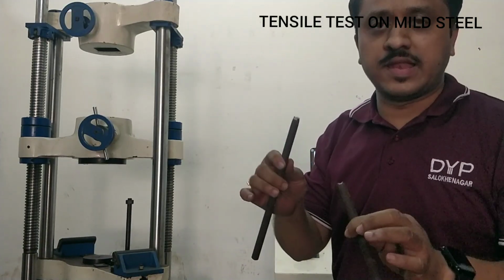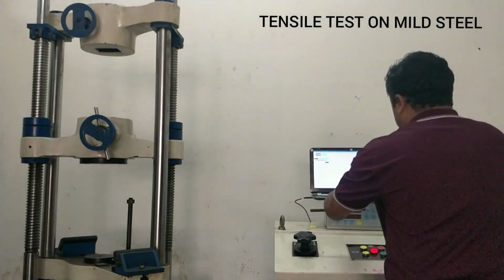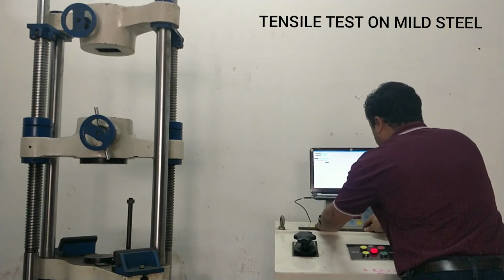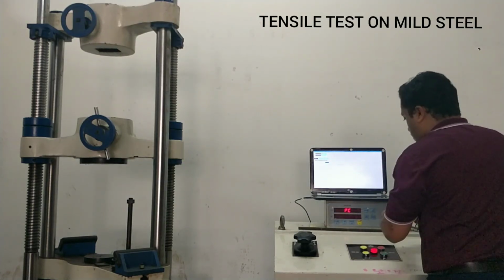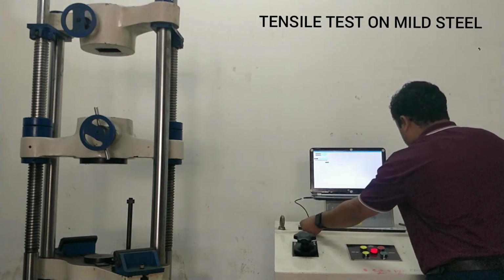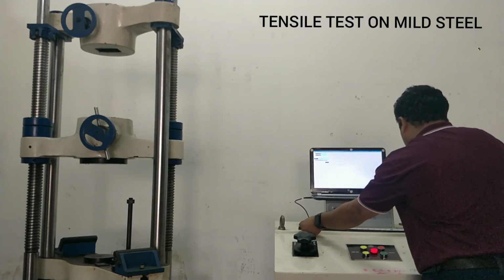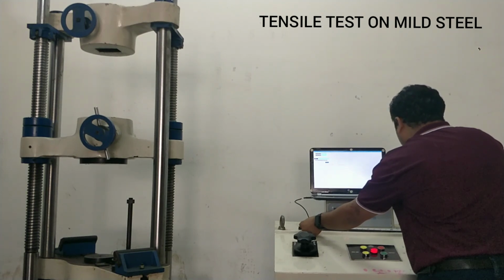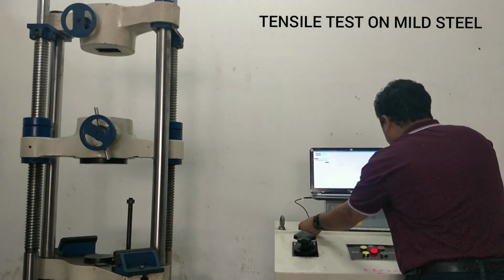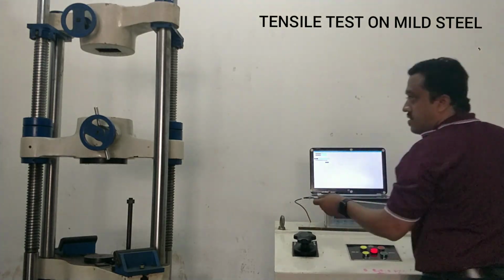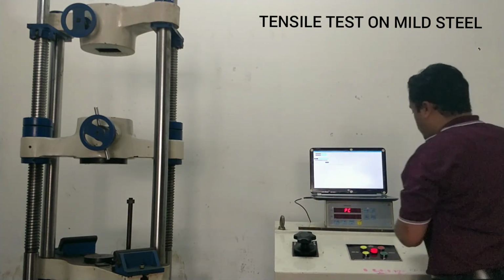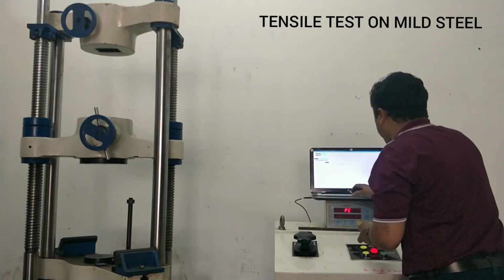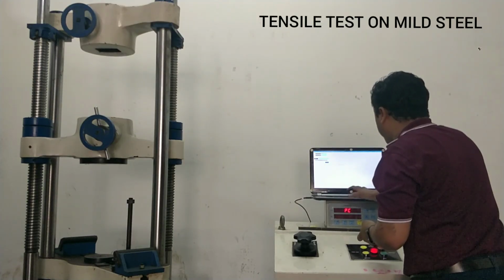Now we will measure the final length of this bar using the tape. The final length is around 465 mm, meaning 46.5 centimeters. So we write here 465 mm.